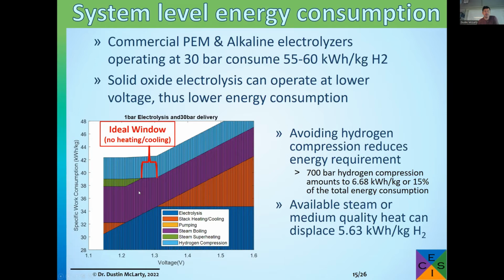Then you have a significant amount, in the purple here, of the heat you need to produce that steam. And then at really low voltage, you actually need that supplemental heater to boost the steam heat, because at these low voltages below the thermoneutral voltage, your electrolyzer would actually be cooling itself. So we need to superheat the steam so that steam can provide the extra energy into the electrolysis itself.